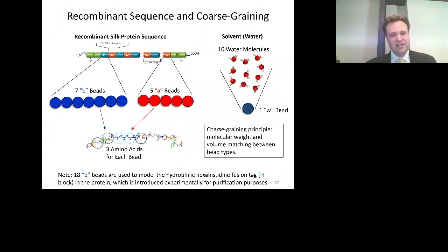So the way this modeling is resolved is we use different levels of modeling. The main tool we're going to talk about today is the mesoscale coarse grain modeling. What it does is resolve about 3 amino acids for each bead or particle. We then have the capital B, which David talked about, which is the building block in these sequences A and B, and the terminal pieces as well in the future. It really is resolved by several of these small b particle letters. You can see that we can thereby control the sequence length as well. So we have really a one-dimensional description. It's a one-dimensional sequence which can actually fold, of course, into three-dimensional shapes.